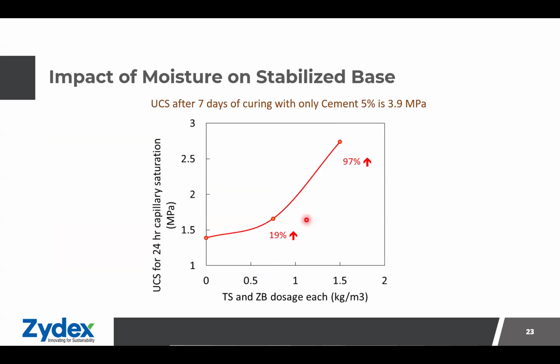This is reported in terms of the unconfined compressive strength. Let's say we have done the regular UCS casting, and after 7 days of curing with only cement, we get a UCS value of around 3.9 MPa. But after 24 hours of capillary intake, when we measure its UCS value, it drops to around 1.4 MPa, which is significantly less, almost less than 50% of its value.